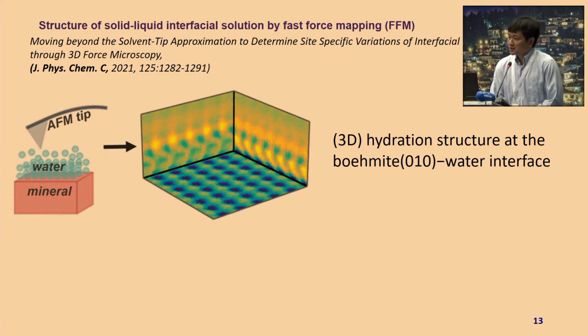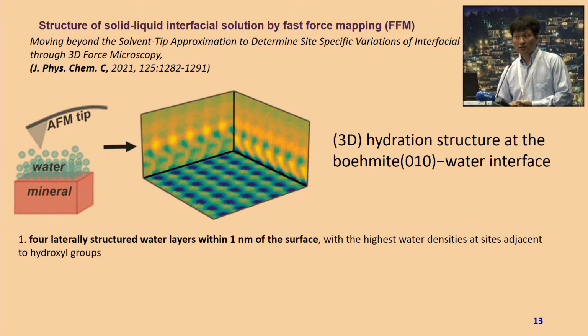And one example regarding the technology, this is by AFM, is the fast force mapping. He was able to show the structure of the solution near the surface of the solid, and he demonstrated in this system, the boehmite water interface. There are four laterally structured water layers within a very thin layer, one nanometer of the surface, and the one closest to the surface has the highest density for the water.